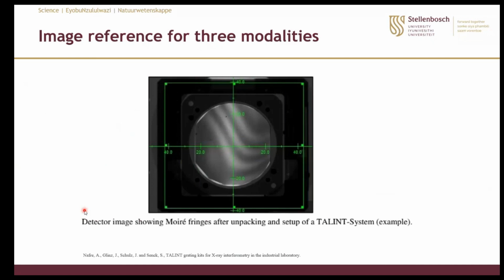And then once you have this moire fringe, you can work with it by fine-tuning it using a micrometer screw on the last 2 gratings and getting image references for the 3 modalities, which are the absorption contrast, the phase contrast, and the dark field imaging contrast. The fine tuning is done in such a way that there will be a rotation around the optical axis. I forgot the term, but hopefully I'll remember it.